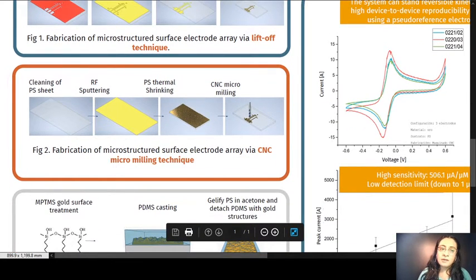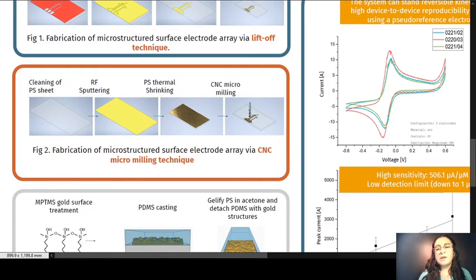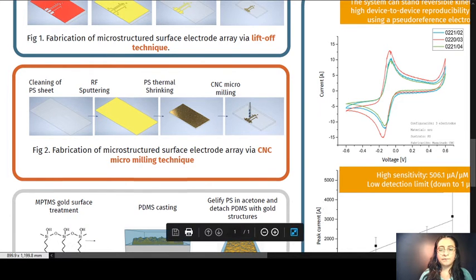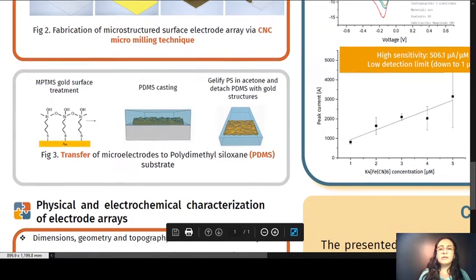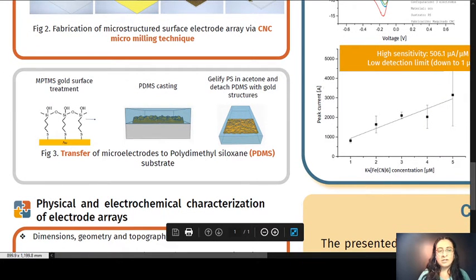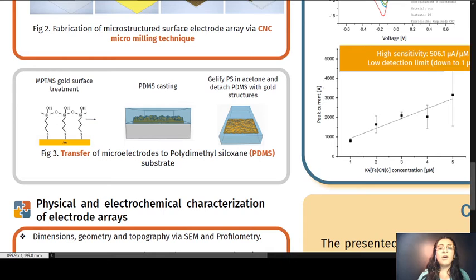In the second method, no stencil is used, and the shape of the electrode is defined on the shrunk polystyrene slab by CNC micromilling. Since the shrinking of the polystyrene induces the wrinkling of the metal layer, these can be transferred into flexible substrates such as polydimethylsiloxane slabs. To do this,